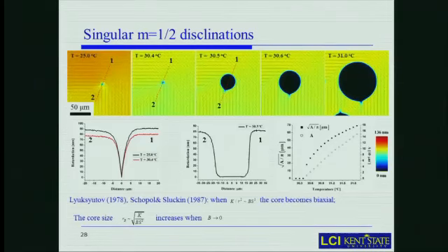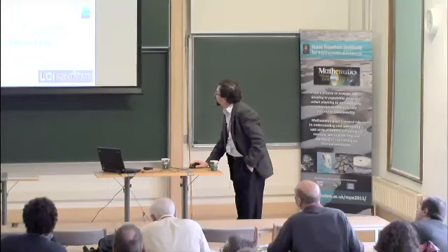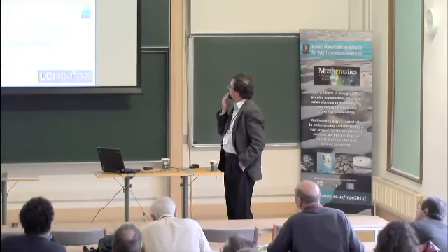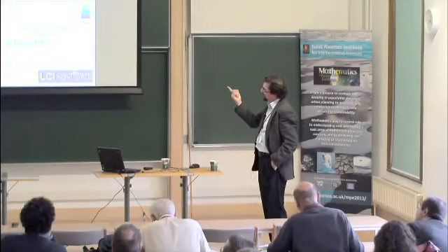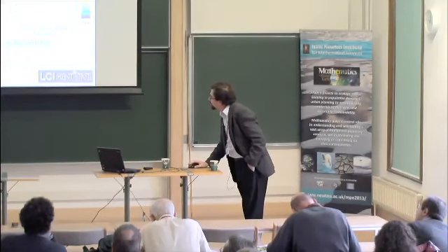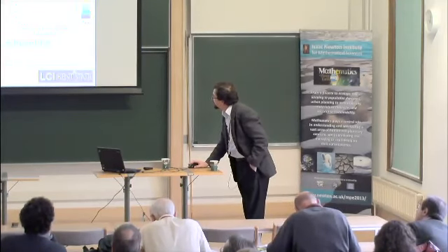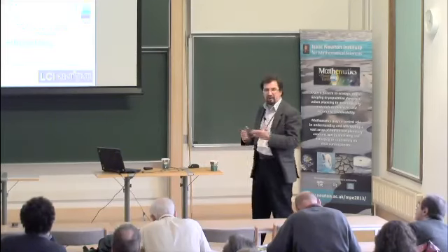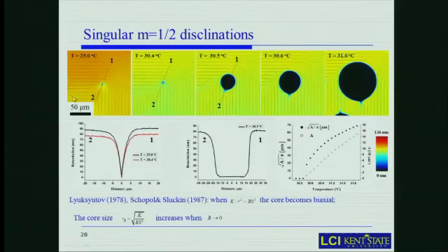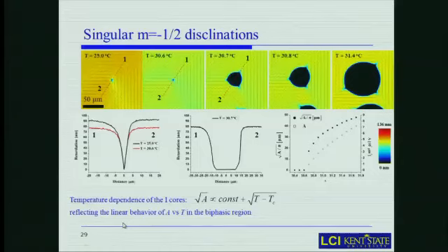So it's interesting that in the case of chromonics, the scale over which these changes take place is much larger than the molecular scale typically observed in thermotropic liquid crystals. And apparently, it's associated with the fact that in this case, the so-called B constant in the Landau-de Gennes expansion is very small, which explains the very large radius of the disclination.